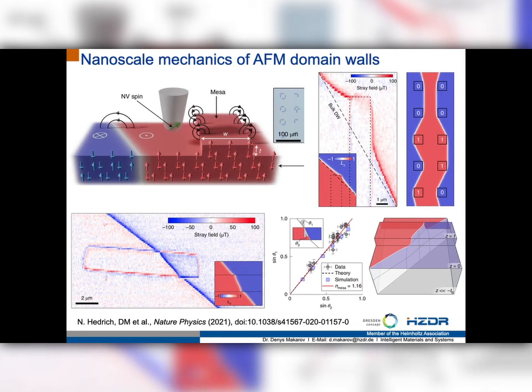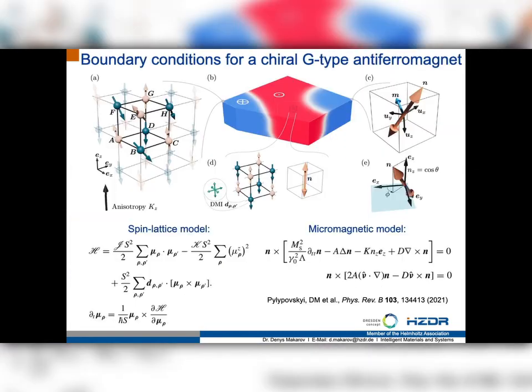This you can simply show even on a prototypical collinear antiferromagnet like chromium oxide, where you have a single crystal with topographic patterns like a mesa patterned here. And you will see that the domain wall, when it interacts with this mesa, is interestingly modified. For example, it can be pinned, it can be deformed. As you can see, you can have a very special S-shaped curve in this material. The pinning can be so strong that you can even speculate about the possibility to create a memory concept based on domain walls in such patterned antiferromagnetic materials. So boundaries definitely affect the properties of those systems.